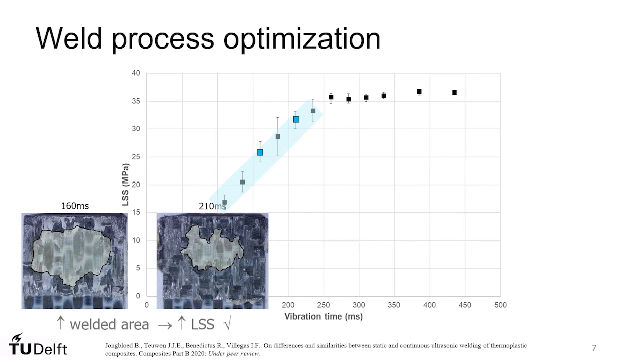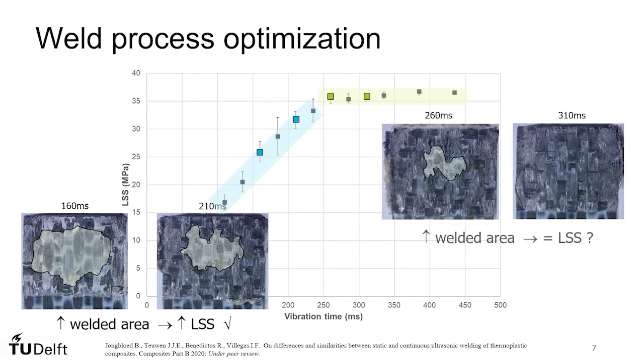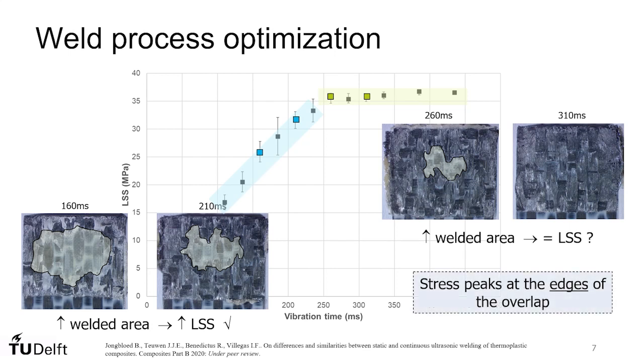Based on this trend, one could expect to find no changes in the amount of welded area in the second region of the graph, where the single lap shear strength remained constant. However, the fracture surfaces showed otherwise, indicating that after a certain threshold, the single lap shear strength values did not allow us to discriminate anymore between partial and fully welded overlaps. We believe this is due to the stress distribution during the single lap shear test, in particular the fact that the stresses are much higher at the edges than anywhere else in the overlap. Therefore, the quality of the weld at the edges of the overlap can be expected to contribute more towards the final strength value than the quality of the weld in the center.